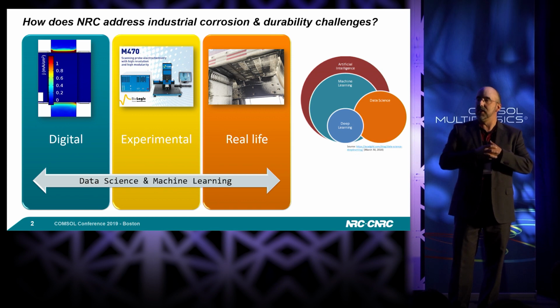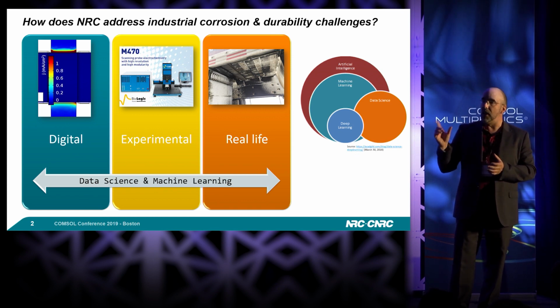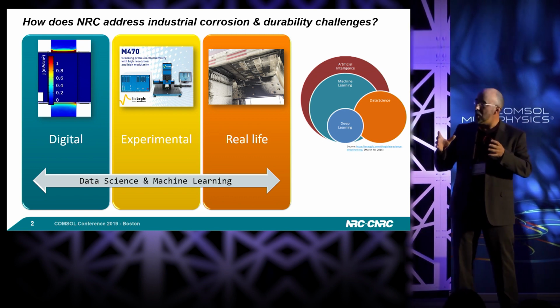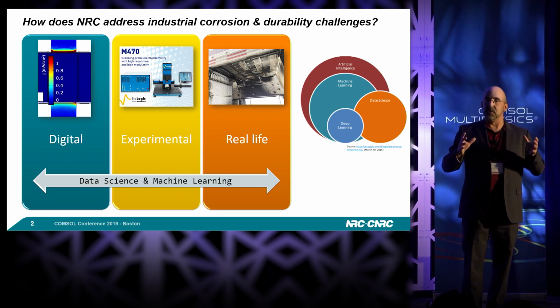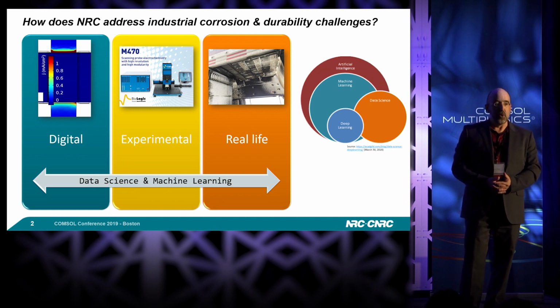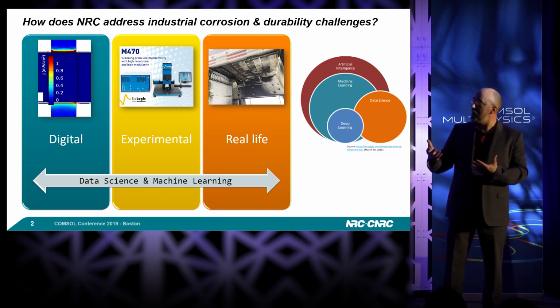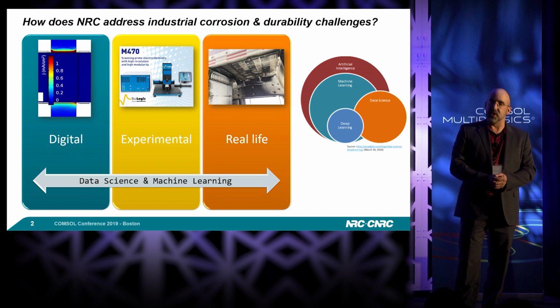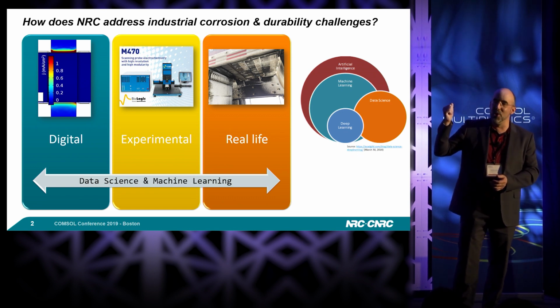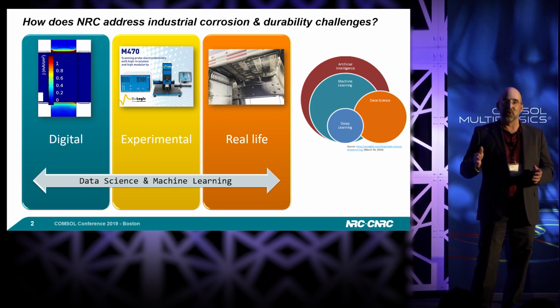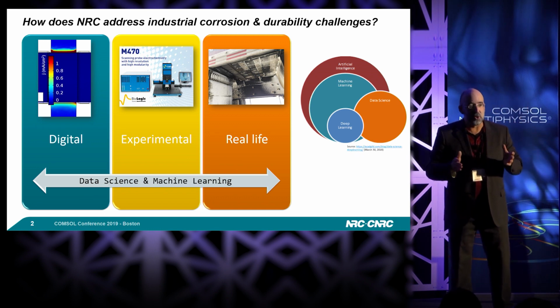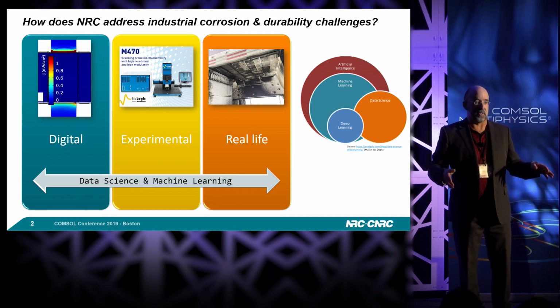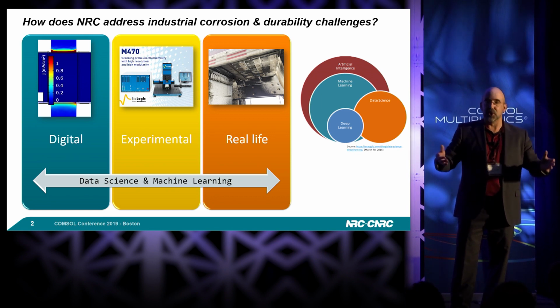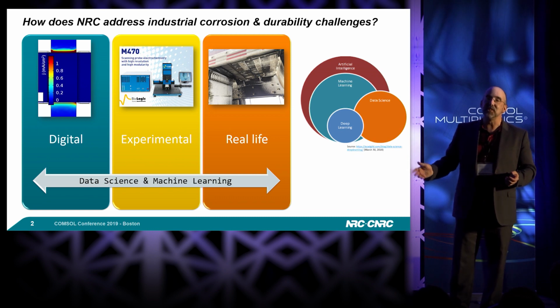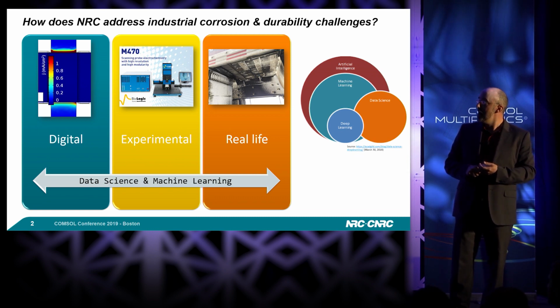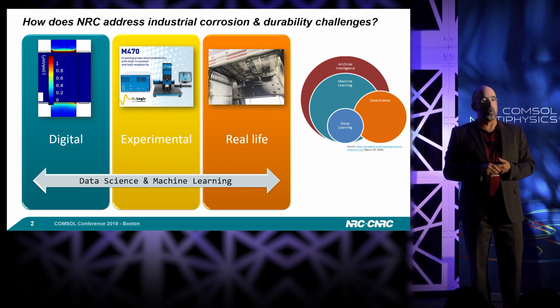If you look at those standards, let's say you take 100 of those cyclic standards, you will probably find that 95 of them mention a step at a temperature of 60 degrees C. So the question here is, if you consider a car under a situation that provokes corrosion, do you really think you will see a temperature of 60 degrees C? I'm from Quebec. When we see corrosion, usually we are at 0 degrees C or below. So 0 degrees C for galvanic corrosion is the worst temperature. Above that, it decreases. Below that, it decreases. At 60 degrees C, let's say you have some traces of salt water, it's going to dry in seconds. So it doesn't make sense to work at 60 degrees C. So what I can tell is that most of those standards cannot rely on real life.